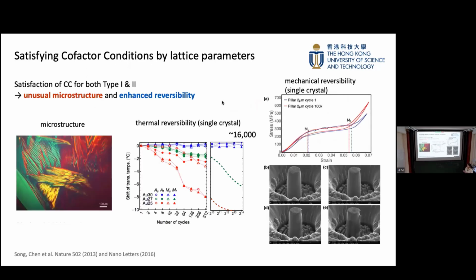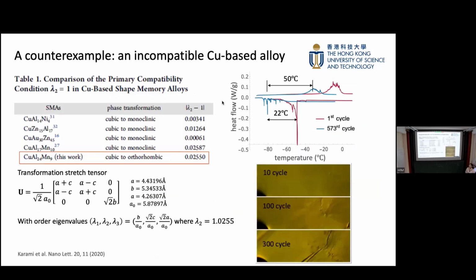Okay. So here I want to show one example. We find that there are some other compatibility conditions. Remember, this is still in single crystal. In addition to the middle eigenvalue of the stretch tensor equaling 1, there is the cofactor condition. That is, if we have twin laminae, and these twin laminae satisfy some further condition, the cofactor condition, then we find the material can be similarly reversible, also mechanically reversible. I don't want to talk a lot about this material. This material has been presented many times, but today I really want to present a counterexample.